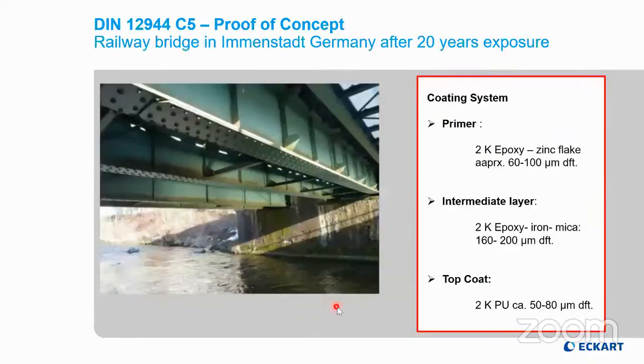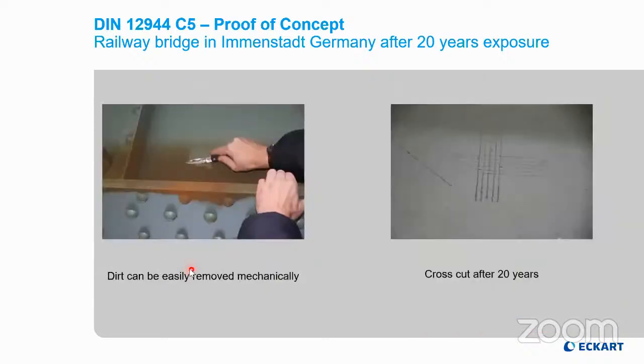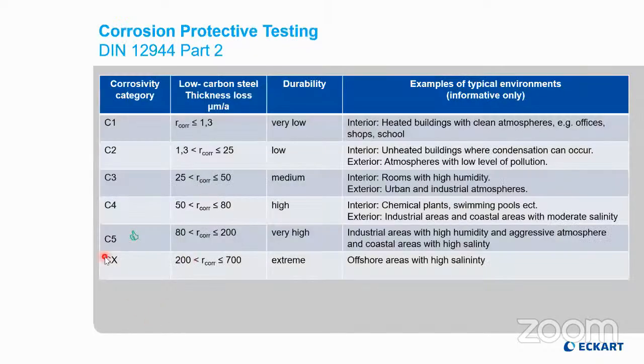In addition, some years back, we started to coat a bridge in the southern German vicinity of Immenstadt nearby Munich with this 3-layer paint system as just described. And this is a railway bridge across a small river. And after 20 years of exposure, the railway bridge still exists and the corrosion protection still is working. And you see this at a cross-cut test after 20 years. And you also see that there is some dirt and surface rust occurring on the bridge that can easily be removed from the surface. So we believe that we have fulfilled this C5 class and we can fulfill it.